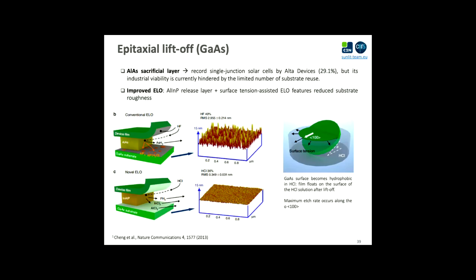So this is really a time-consuming process. The best I know is based not on aluminium gallium arsenide, but on the phosphide materials using HCl instead, which has even a better selectivity. This is the roughness of the substrate after the epitaxial lift-off whenever you use HF, and this is the roughness, way lower, when you use HCl. Nevertheless, it takes about 8-9 hours to remove the epi layer out of the 2-inch wafer. So it's really slow.